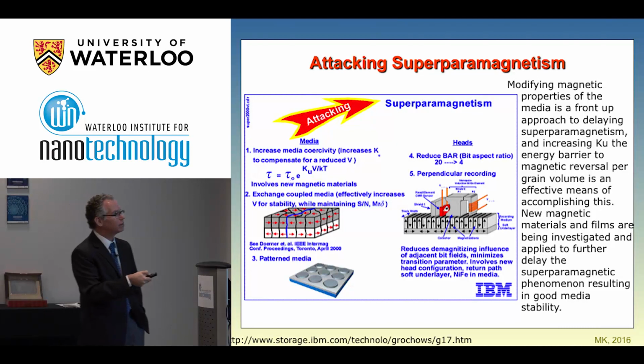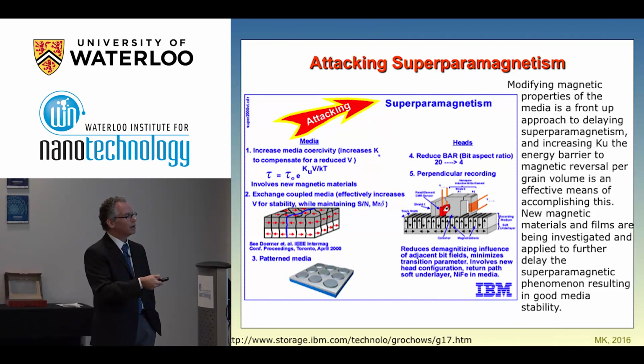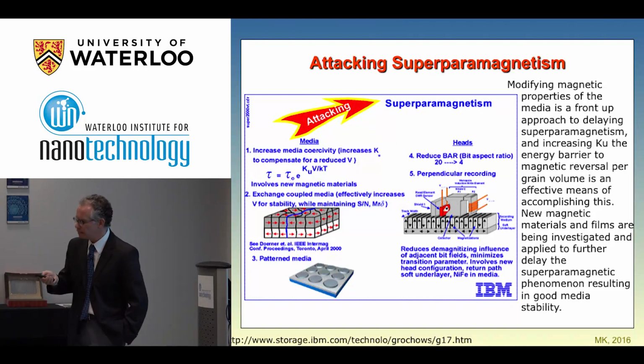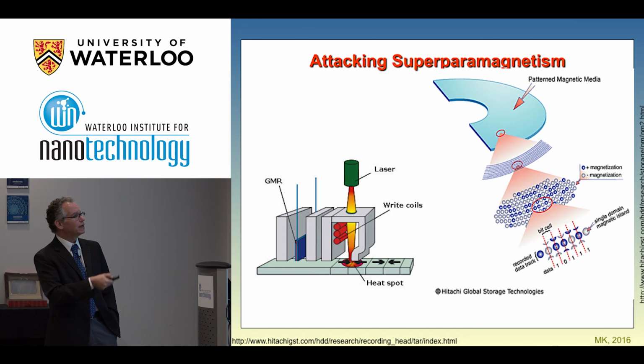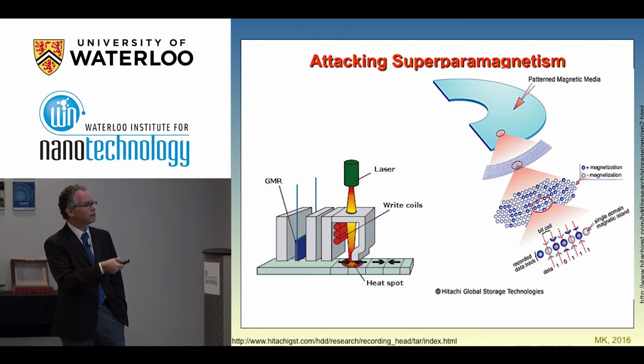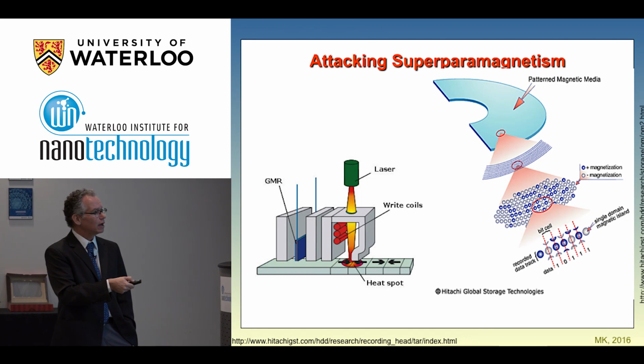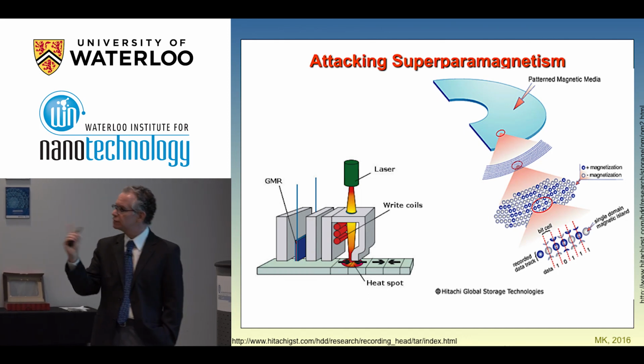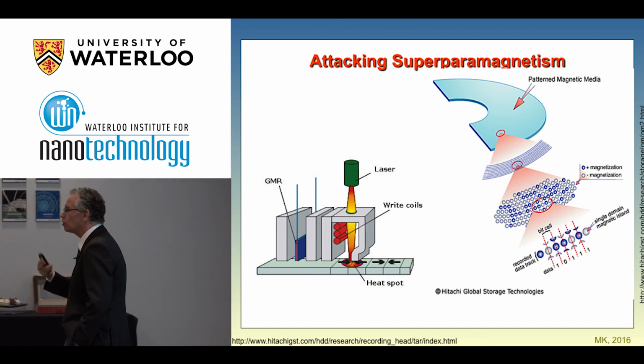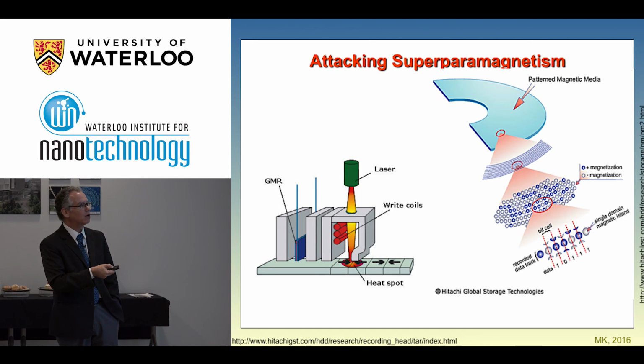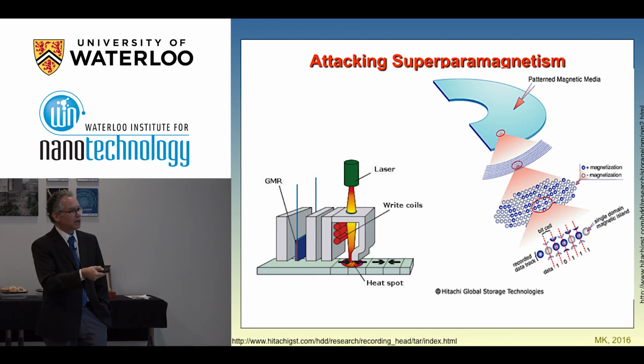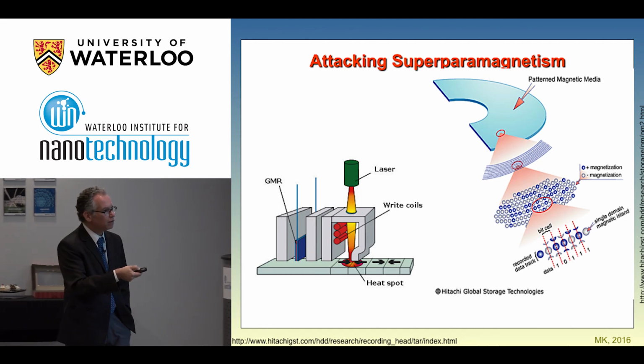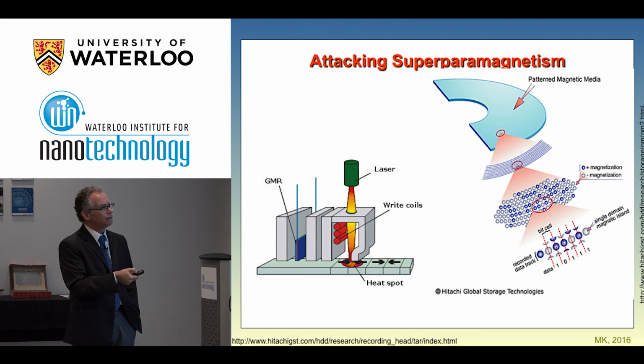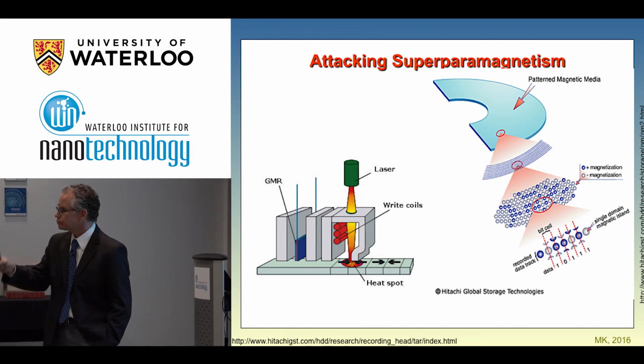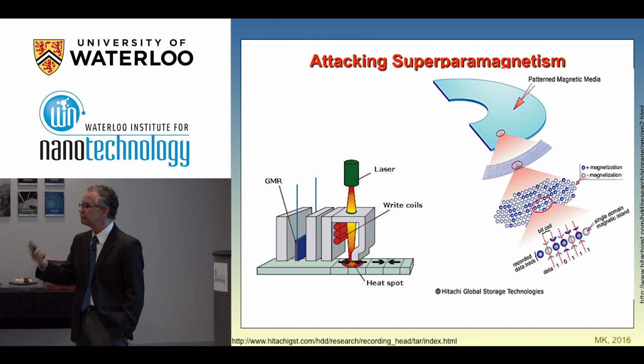So they tried different exchange-coupled media. They changed to perpendicular recording, patterned media. They tried everything. And some of these technologies came down. So one idea that came from Hitachi, for example, was to make a hybrid system with a magnetic system with a laser in order to heat locally in order to make this magnetic system change. But of course, this gives more and more complexity to the hard disk, and it didn't work out. Another idea is to make a patterned magnetic media in order to record one single bit in each of these nanostructured materials. So this is something that is feasible to do. The problem is now how to read this information in a very quick way.